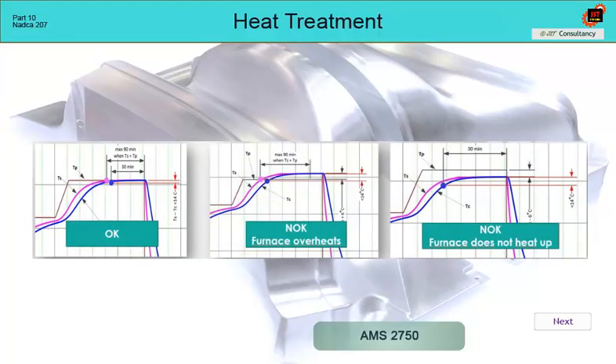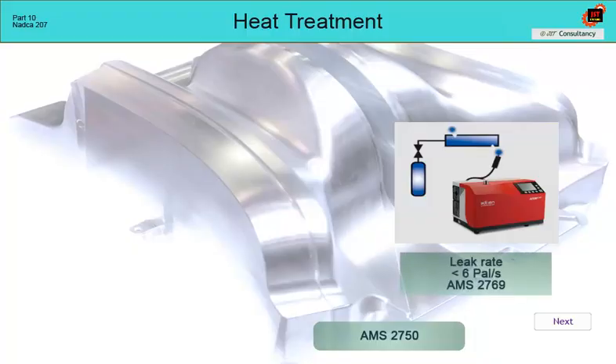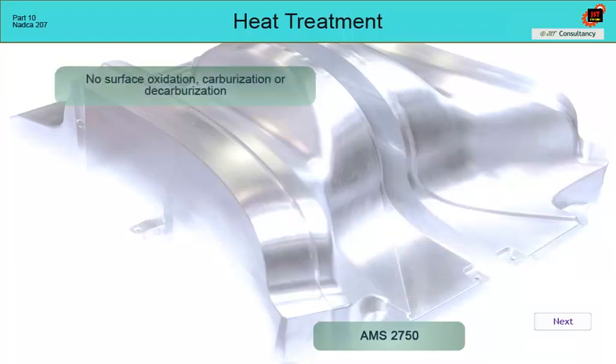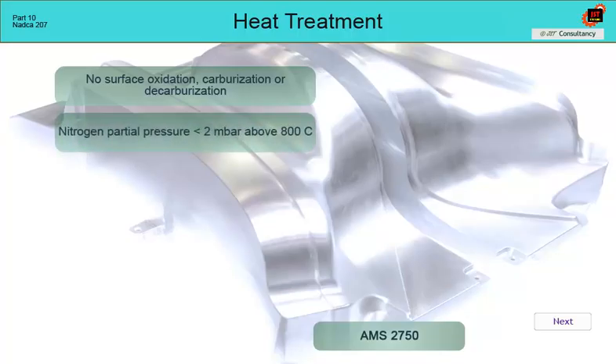The vacuum furnace must be leak controlled with a maximum leak rate of 6 Pascal liters per second per AMS 2769 for vacuum heat treatment of steels. It must be ensured that no oxidation or carburization or decarburization of the surface of the parts occurs during the process. The furnace should be able to work with a nitrogen partial pressure of up to 2 millibars at temperatures above 800 degrees Celsius to eliminate the evaporation of alloying elements in the steel.